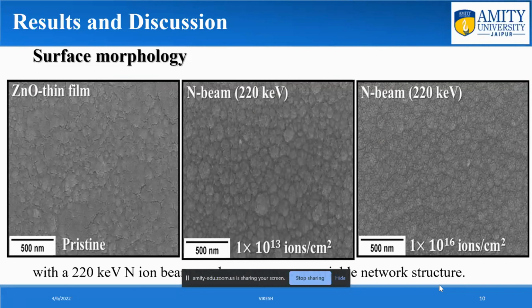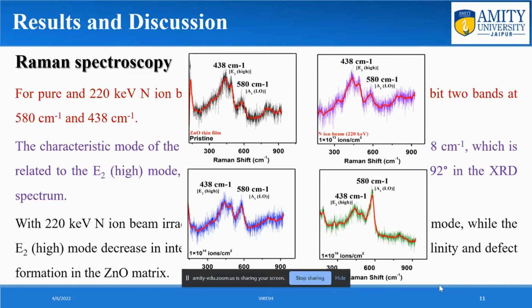With 220 keV nitrogen ion beam irradiation, the intensity of A1(LO) mode increases, while the E2 high mode decreases in intensity, which is responsible for reduced crystallinity and defect formation of ZnO matrix.